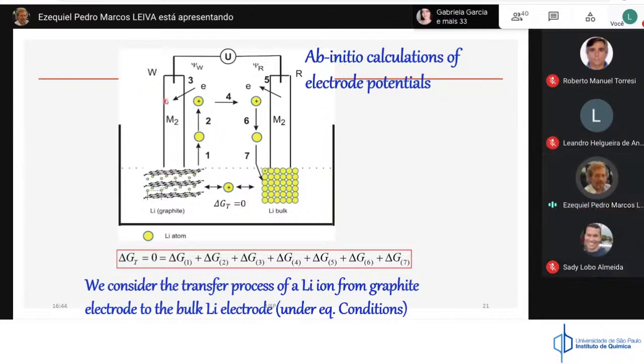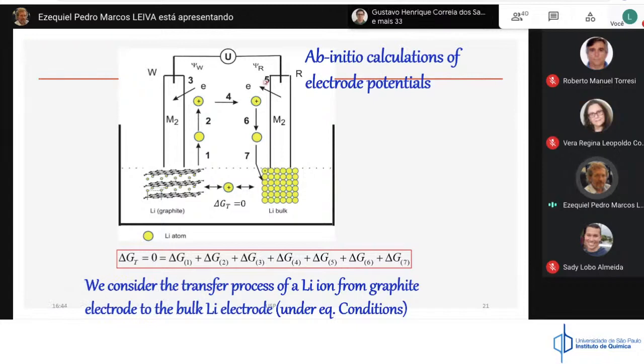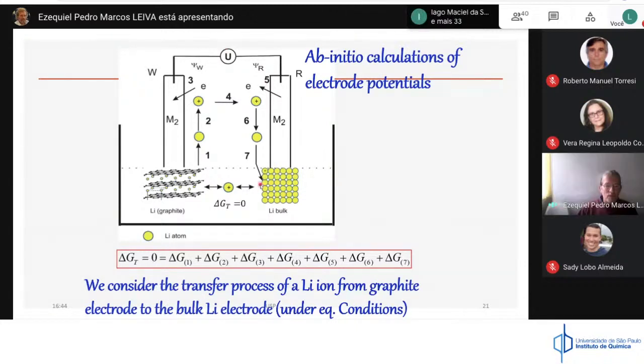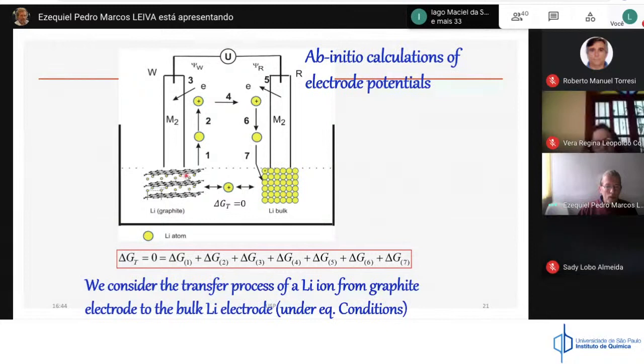If you consider an electrochemical system, and let's say you use a reference made of lithium bulk material, and you take here the material you have under consideration, if this system is in equilibrium, the free energy change that you have to transfer an ion from, let's say, graphite into a lithium bulk is zero as long as you are in equilibrium conditions. But you can decompose this transfer of an ion through a number of steps.